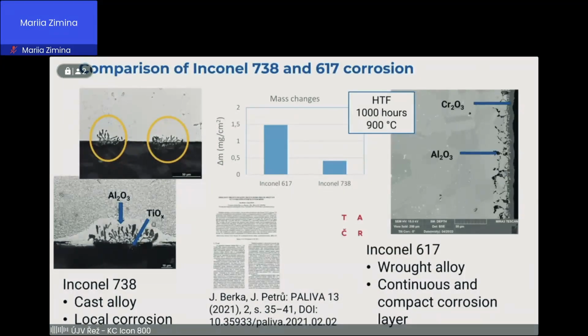So, when I was working on this presentation, I got the idea to compare the results of high temperature corrosion of Inconel 738 obtained during the finished project, and hot corrosion of 617. As I said, the corrosion of 738 alloys was only local, compared to 617, on which a compact layer was formed, and also the mass gain of Inconel 617 was about three times higher than that of Inconel 738.